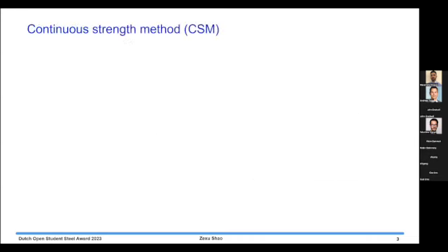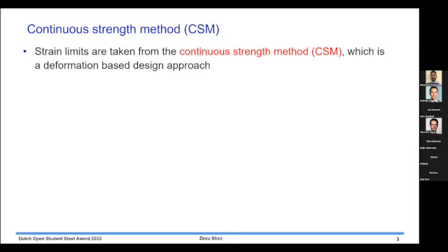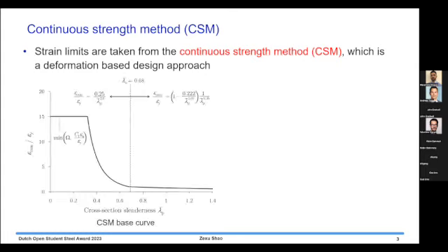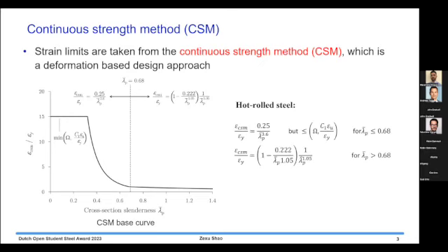So what is strain limit actually? The strain limits are taken from the continuous strength method. As a deformation-based design approach, the continuous strength method features a base curve that defines the level of strain a cross-section can endure prior to failure. The CSM strain limit is represented as a function of the local slenderness of the full cross-section. So for hot rolled steel, we can calculate the CSM strain limit using these two formulas.